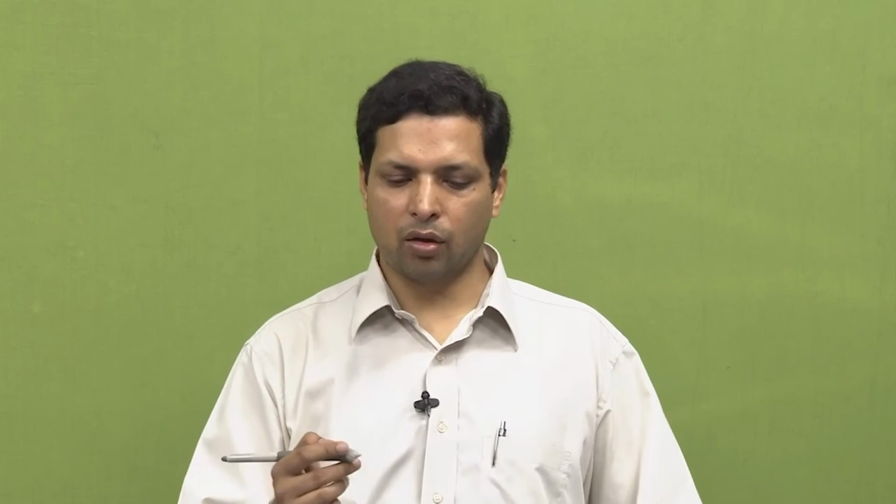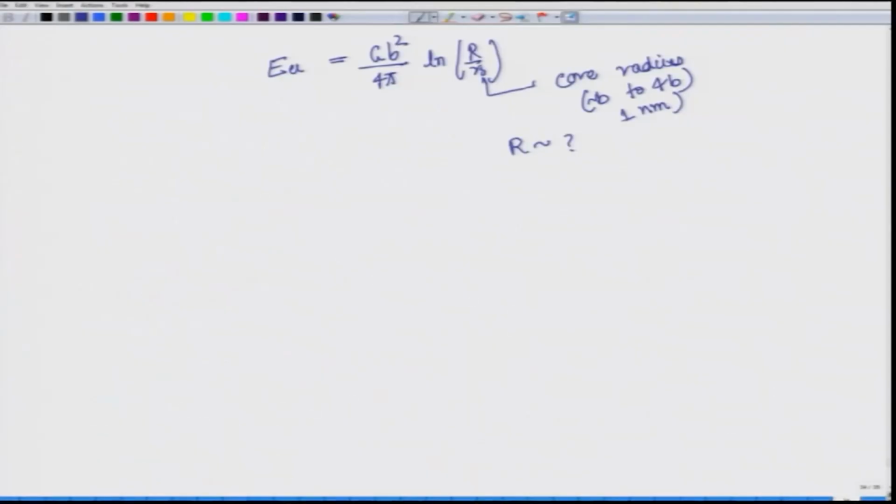Yes, it is true that the elastic strain energy component becomes smaller and smaller as we keep increasing radius R, the uppercase R, but there should still be some way to say what this R is, and a simple solution for that is to take R as the grain size, basically d by 2. If the grain diameter is d, then R will be equal to d by 2. So, that also solves the problem. Now, we know both the parameters over here, R and r naught.